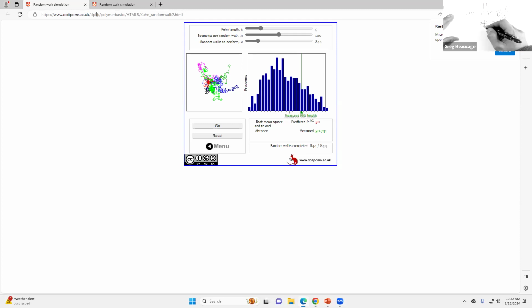For a random walk, like a diffusive walk, the average of that cosine term is going to give you 0, because it can just as easily go forward as backwards. So they cancel out, or you can go up or down and cancel out. So this term is 0, and you just have the first term left, and that's nL squared. So that directly gives you this. That's the definition of that R squared. If it's a drunken walk, it has to be nL squared. Random walk's law. So anyway, that's one part of this whole picture of what's going on with this.